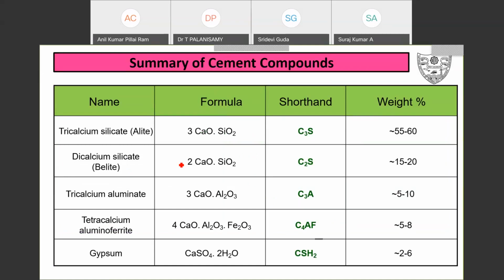Now, tricalcium silicate, this is called alite. All of you know about that, alite. This is called C3S. We have 55 to 60% of the weight. Then dicalcium silicate, this is called belite. It's called C2S. Then tricalcium aluminate, 3CaO Al2O3, C3A, is 5 to 10%. This is 15 to 20%. Then tetracalcium aluminoferrite, 4CaO Al2O3 Fe2O3, C4AF, we have 5 to 8%. Then gypsum, all of you know the role of gypsum, CaSO4·2H2O, 2 to 6%.